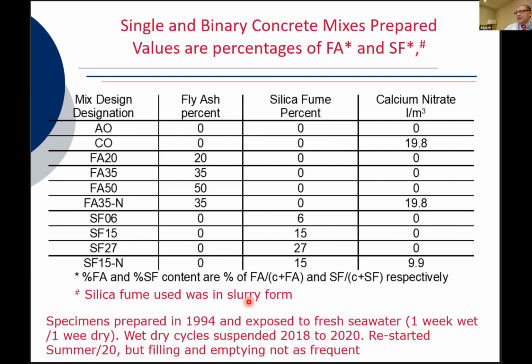From 1994 to 2018 or so, they were subjected to wet and dry cycles, 1 week with seawater. I ran out of students that wanted to do this kind of pro bono. So for about 3 years, we interrupted the adding of the seawater. These samples are exposed outdoors, as you'll see in a moment. But when we started the first year of the 3D URLE project, we reinitiated the wetting with seawater, just not as frequently as we used to do before.